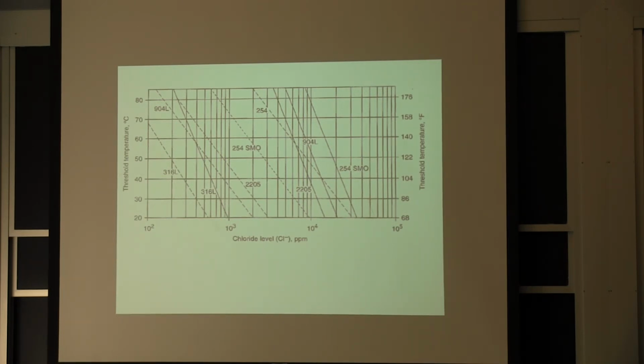So you can see here, depending on your temperature, at ambient it would take 1,000 ppm chlorides, but you go up in temperature, if you're exposed to the sun or if you have a heat source, and then all of a sudden your resistance goes down. This plot, and a lot of these things, are the same way. They're just nominal values. If you have this bead blasting process, if you have the brushing, it goes down. There's no absolute value here. It's only based on a certain nominal roughness and mill finish normally. It depends on how the test was conducted, but it's not an absolute value. It's more an indicator, and then you have to work from there and see specifically what could have happened.